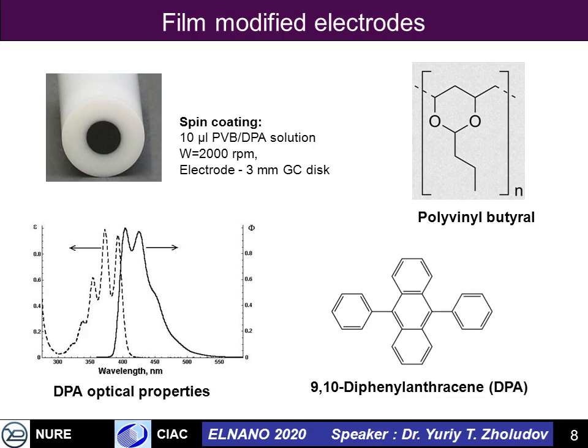For testing this home-designed spin coater, an ECL system was made. We used a glassy carbon disc electrode, shown in the top left picture. In order to fix it on the spinning plate of the spin coater, a special adapter, which is not shown here, was fabricated.